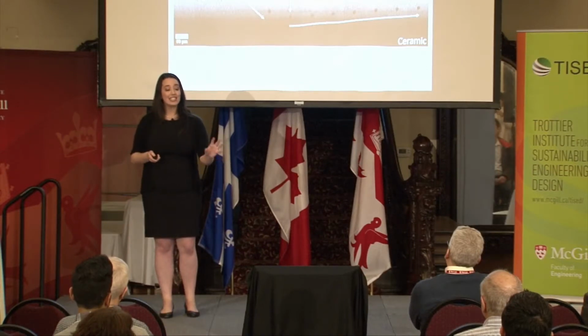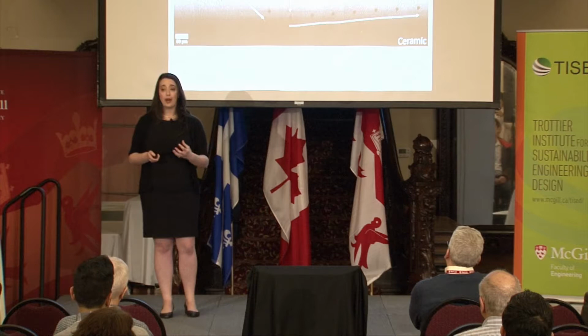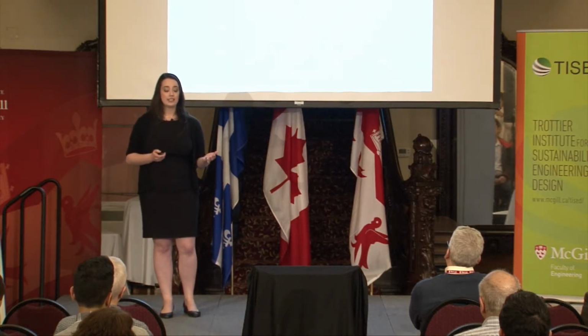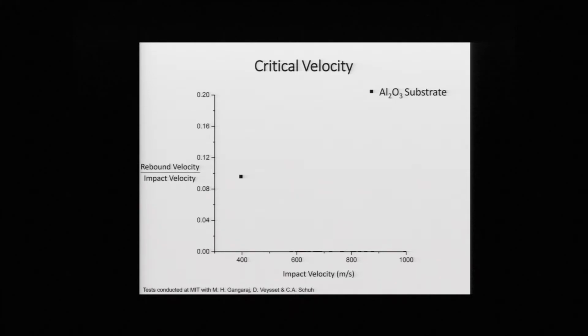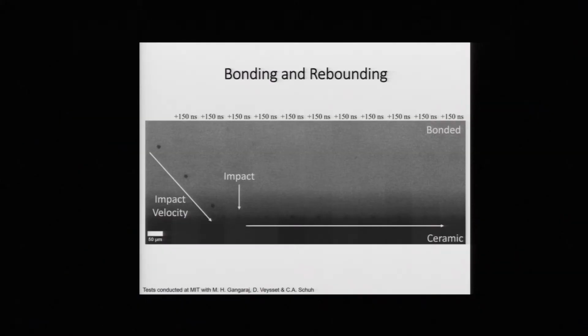And if you were to take this particular experiment and plot it on a graph with respect to the impact velocity, you would get this. And if you repeat this multiple times, you would get a series of points that show you how that coefficient of restitution varies with impact velocity. And eventually, you'll get adhesion. And this is an image that we observe when the particle does not rebound.